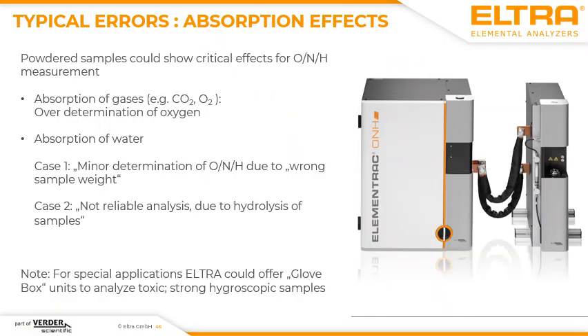As for CS analysis, you can have some very strange absorption effects, which means a highly fine, divided powder, for example, could absorb CO2, which again could show higher oxygen contents. The other thing is the absorption of water.